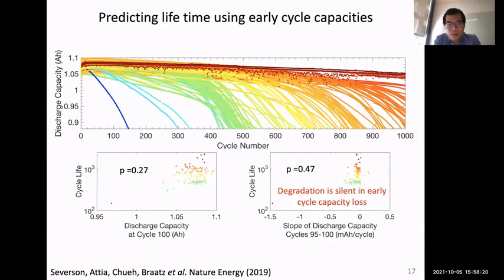And when we do the full analysis, we find that the performance of the battery in the early cycles does not correlate well with its cycle life, which is the number of cycles it will last until it degrades to 80%. Similarly, if you look at the slope, the degradation rate at the early cycles, it also does not predict very well the cycle life of the battery. So in other words, degradation is mostly silent in the early cycle capacity loss. The battery is degrading, but not in a way that can be correlated to predict the outcome.